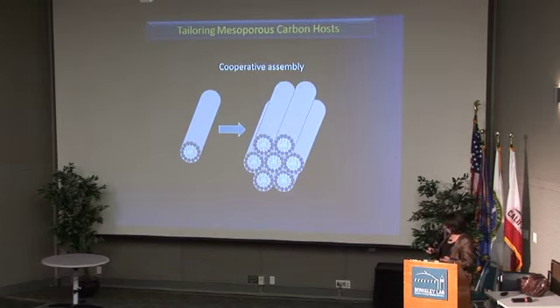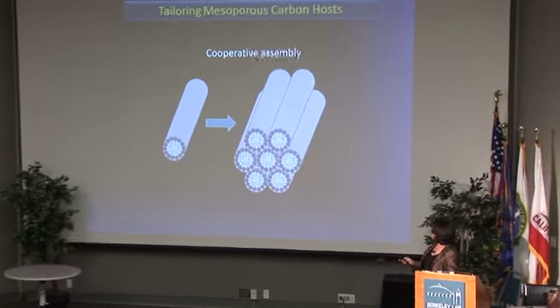We have been addressing this problem through the design of porous carbons, because those are required for the host and they're required to electronically wire the system. This shows a typical cooperative assembly using surfactants to assemble a silica, which is then converted to a carbon. This is well established by many others in the field, including Galen Stucky at Santa Barbara and Ryong Ryoo in Korea.